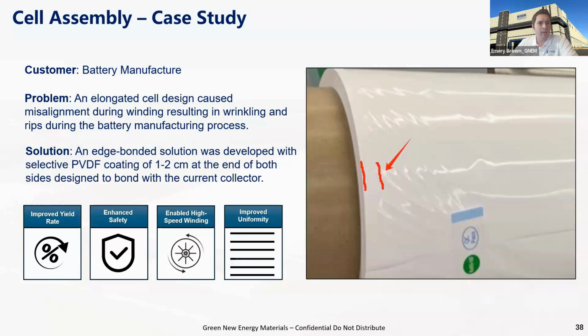Our parent company and the cell maker worked together and developed what we call the edge-bonded solution. It had a PVDF selective coating right on the edge, about 1 to 2 centimeters on the edge of the roll, as you can see there on the right in the picture. This was designed to bond with the outer edge of the current collector, with some of the exposed current collector. When they got this right, it rapidly improved their yield rate and their uniformity during manufacturing. It really enabled high winding speeds and enhanced safety.